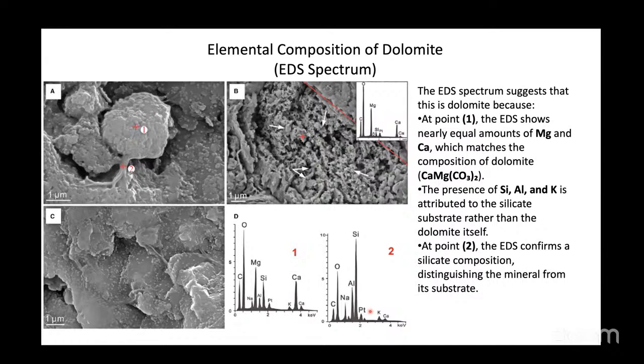Finally, at point 2, the spectrum shows a strong silicate composition, confirming that we are dealing with silicate minerals in the surrounding area. This further helps us separate the dolomite from the silicate substrate and reinforces our interpretation of the sample. By looking at the EDS data in this way, we can be confident that the mineral in question is indeed dolomite, and the other elements are likely from the substrate rather than the dolomite itself.